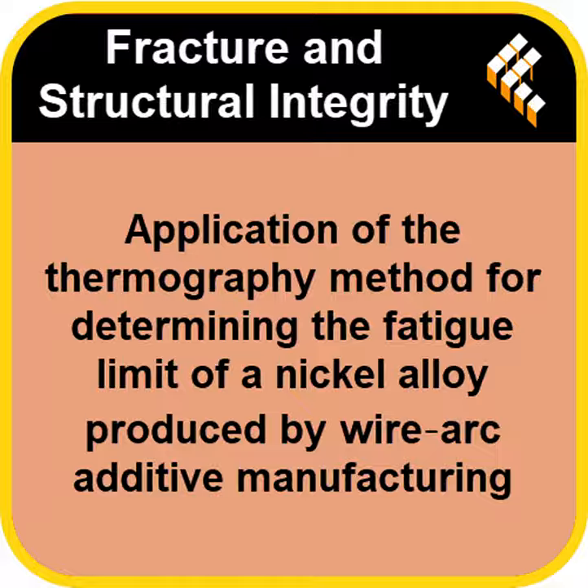And to measure that temperature shift, which could be tiny, they must have needed some seriously sensitive gear. Oh, absolutely. The infrared camera they used had incredible thermal sensitivity. It could detect temperature changes as small as 0.02 of a degree Celsius. Wow. And that precision is key because you want to see the damage starting long before the material actually feels warm to the touch.